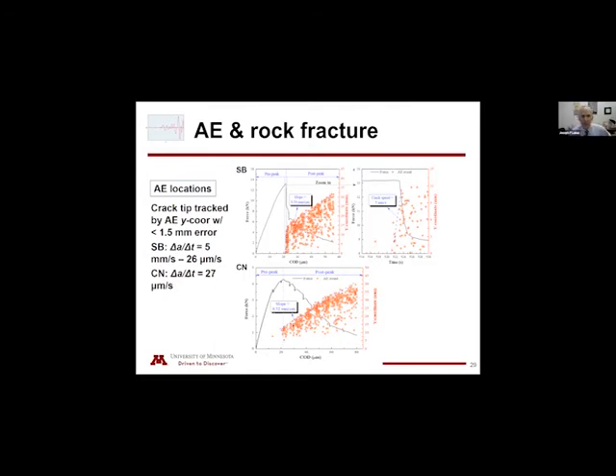Okay, and this is the mechanical response. We're looking at now the smooth boundary is the upper one, and I showed you this result earlier. I don't have the load point displacement, but that is that severe snapback that takes place. Also plotted on this diagram is the Y coordinate of the acoustic emission. So, of course, we have the XYZ coordinates, but this, that's my timer, so I have 5 minutes. This indicates the, I would argue, the growth of the crack, and this is how we measure the crack speed.